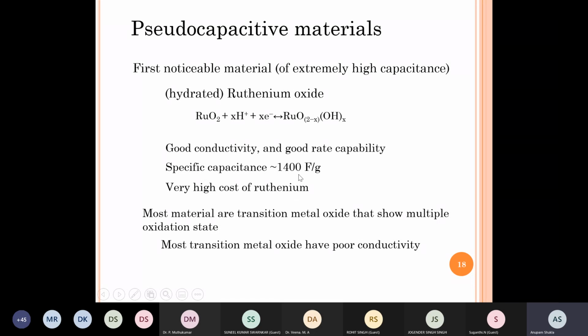This was the first major pseudocapacitive material that brought in this thought into the domain, that pseudocapacitance can be used as a possible electrochemical capacitive device. However, ruthenium, though it showed the path, cannot be commercialized simply because of its cost. Other materials which are used are mostly transition metal oxides. It's not just oxides, but different transition metal based compounds. And most of these compounds have poor conductivity, most of them.